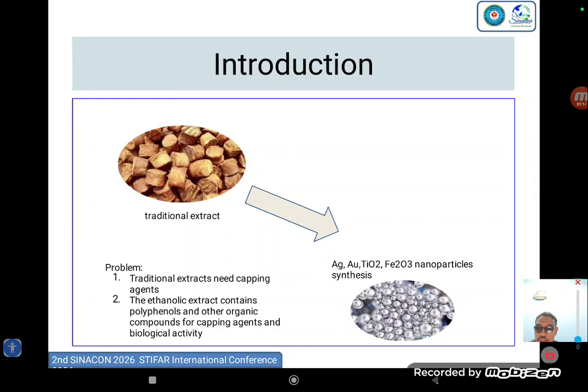Previous research has shown that synthesized silver nanoparticles often tend to agglomerate. To prevent this, conventional methods typically require synthetic capping agents. However, the ethanolic extract of gambir demonstrates its true potential here, as it is rich in polyphenols and other organic compounds. These natural compounds serve a dual purpose. They act as highly effective bioreduction and capping agents to stabilize the nanoparticles, while simultaneously transferring their biological activity into the final product.